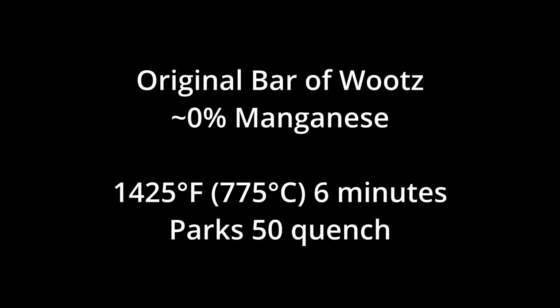So as I mentioned, that first piece of steel he sent me with the very low manganese content, I heat treated it and couldn't get it to harden. So Spencer told me he normally uses 1425 Fahrenheit for 6 minutes and then quenches in Parks 50. I copied that heat treatment, but I got very inconsistent hardness readings, which likely indicates that some pearlite was forming